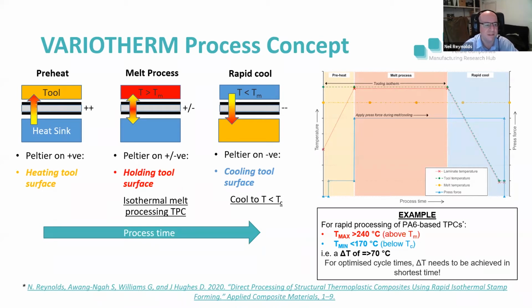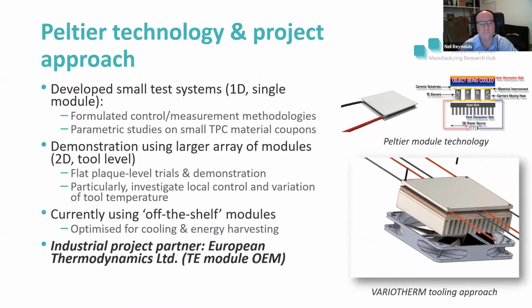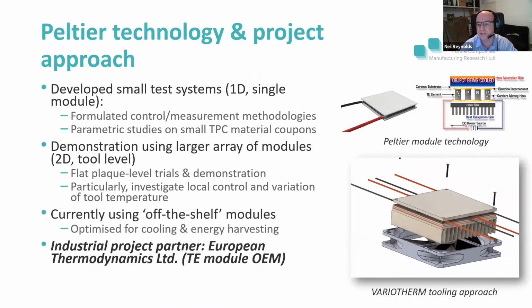Looking at the left-hand diagram, where you can see the different tooling elements, you have the upper tool surface, which is 2 to 3 millimeters thick, the active Peltier element in the middle, and then a heat sink behind that. And that's what I was saying about how you can effectively move the heat around within that system to process the material. Next slide, please.